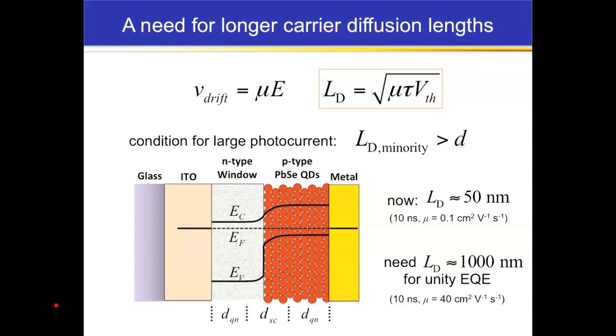So the diffusion length is really important because if we have a heterostructure or a heterojunction type of device like this, we need about a micron thick film in the quantum dot layer to absorb all the light. But of course, if we don't have large diffusion lengths, then carriers that are created back here are never going to escape from the device, and we're going to get a large hit in the current. The problem is that diffusion lengths are thought to be currently in quantum dot films about 50 nanometers. Okay? And this is calculated basically for 10 nanosecond lifetime and 0.1 mobility.